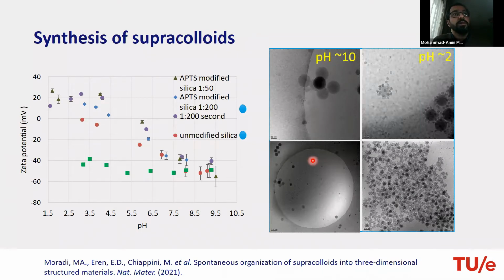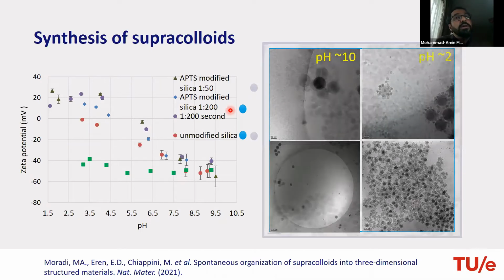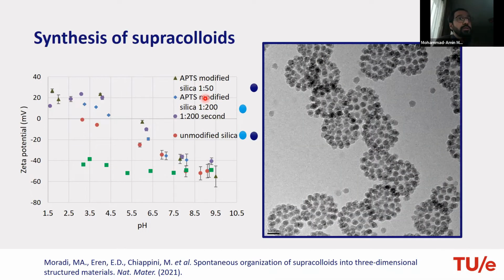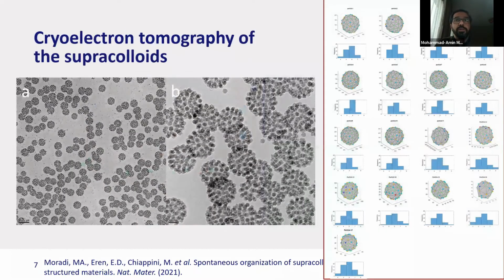So we functionalized our silica materials with different ratios, which later on happen to be the key to shape our supracolloids in a perfectly covered material. As you can see here, we change the charge densities following the curves of pH switch and the zeta potential of the system, and then with a specific ratio of the amino functionalities on the surface of the silica, we could reach almost fully covered supracolloid in our system. But we were not sure whether we really have them fully covered or not.